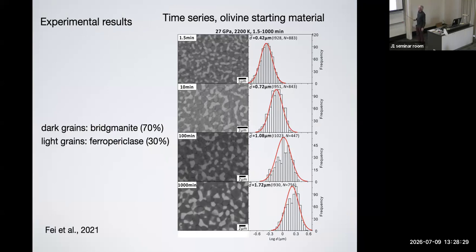Olivine starting material, I'll come back to that. If you take olivine, Mg2SiO4, bridgmanite has a composition of MgSiO3. So you get a mix from the olivine starting material, you get a mix of that bridgmanite, and then the extra Fe and Mg goes into what's called ferropericlase. It's just iron magnesium oxide. And the brighter stuff here, that's the iron magnesium oxide. The darker is the bridgmanite, the perovskite structure.